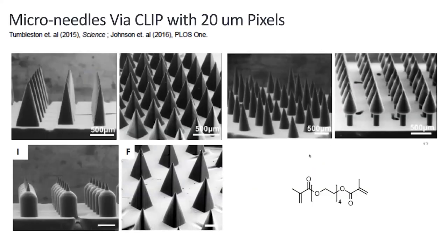So we built one of our printers with smaller pixels. The commercial printer has a 75 micron pixel for the M2, and 162 micron for the L1, the big printer, which is 5 times bigger than the M2. But building a printer at 20 or 30 microns allows you to make these amazing structures, things you actually couldn't make in a fab very easily. Imagine if you were trying to etch silicon and wanted to systematically control the thickness of your etched silicon to make thick microneedles, different thicknesses or different heights or undercuts. You spend more time designing these things than you do printing them with CLIP. These take minutes to print.